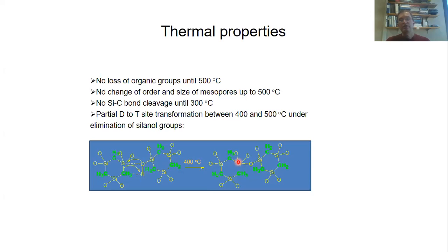at 400 degrees Celsius, you see a lower dielectric constant than at 300 degrees Celsius, because at 300 degrees Celsius, still a relatively large amount of silanol groups are present, while above that temperature, around 400 to 500 degrees Celsius, we get a self-hydrophobization effect in which these silanol groups are eliminated to form less polar silicon-oxygen-silicon bridges, and methyl groups are forming.